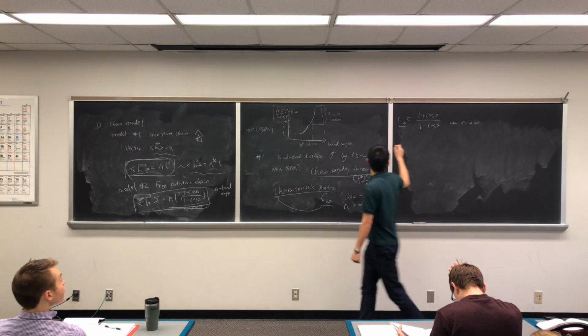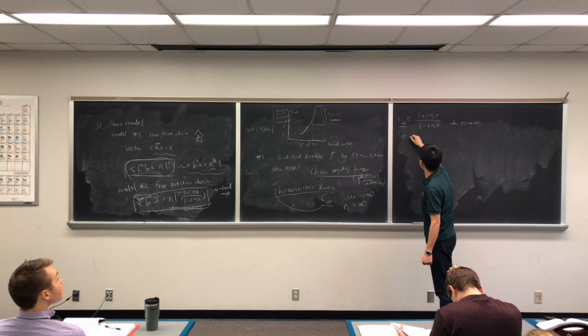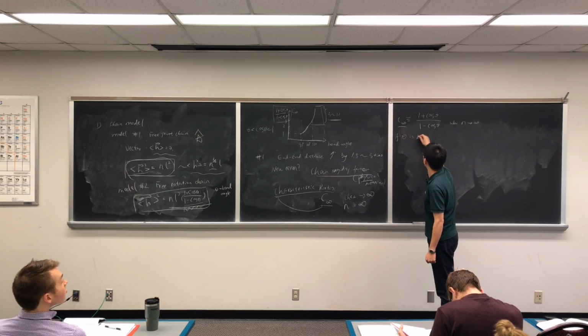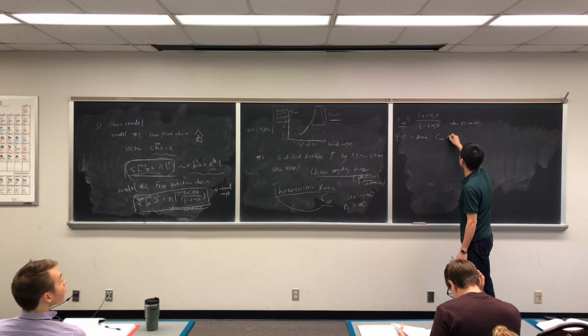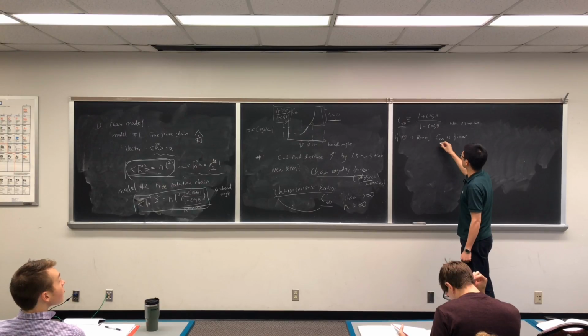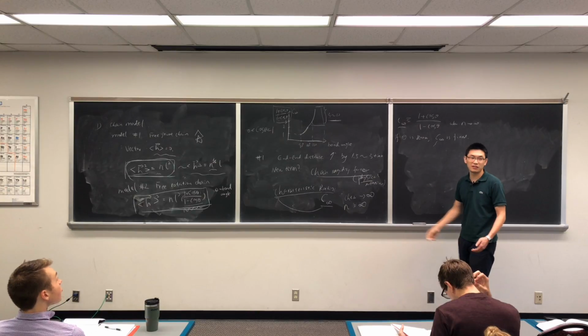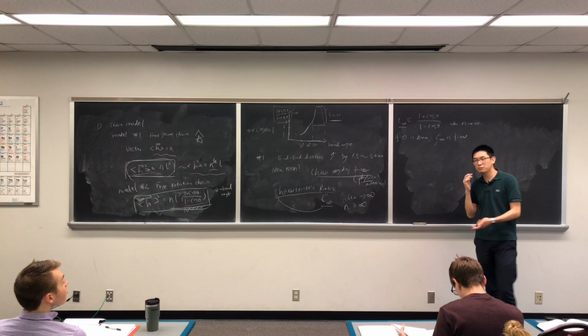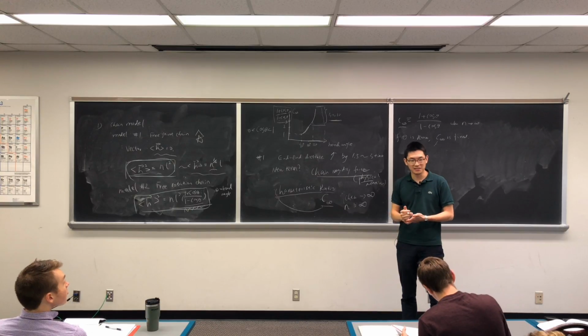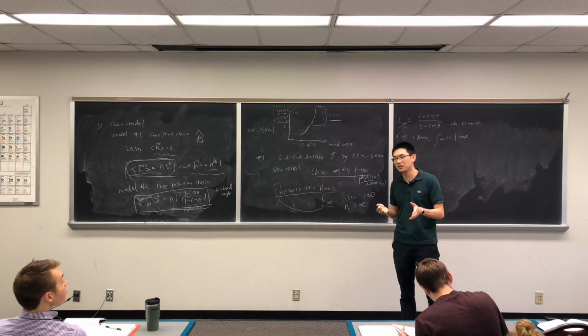And if theta is known, then C infinity is fixed, right? And we talked about that. So for most commodity polymers, from polyethylene, polystyrene, polypropylene, this C infinity is somewhere between 3 to 10.